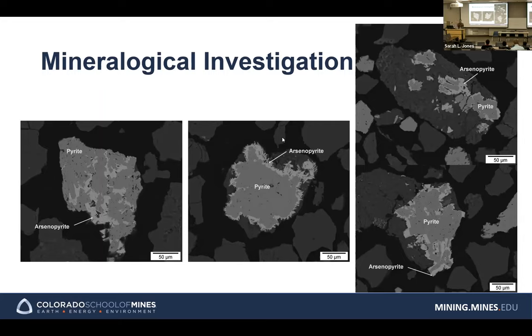Gold can be associated with pyrite, and gold can be associated with arsenopyrite. But the concentration in arsenopyrite is an order of magnitude higher than in pyrite, sometimes 100 times or even higher. So if you have arsenopyrite, there's a chance that the gold concentration in it is much higher than in pyrite. If you don't treat the arsenopyrite correctly, you're going to lose that high amount of gold. So here the arsenopyrite is in the center. And this one is typical, we call it arsenopyrite rimmed around the pyrite grain. The arsenopyrite is on the edge of the pyrite grain and contains higher gold.